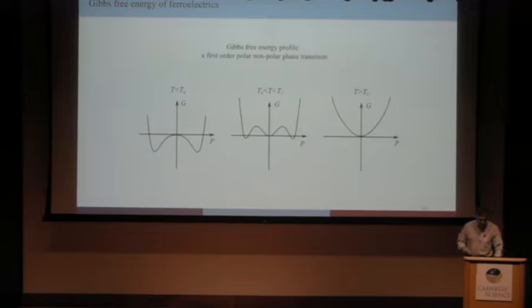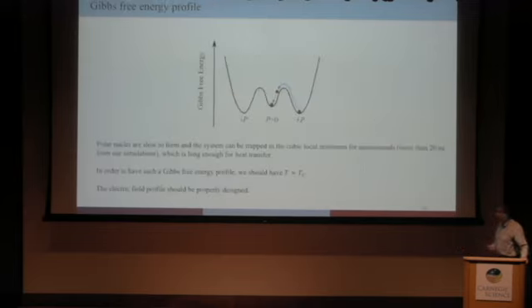And that opens this opportunity for using the latent heat. And so schematically, what we're doing with this electric field is we're driving the polarization away from its favored value, and for certain pulse shapes and durations, it can become convinced that the closest minimum is the p equals 0 one. It'll fall into that minimum and stay there for some amount of time. And depending on how close we are to the temperature at which the zero polarization minimum goes away, or becomes dominant over the positive polarization, that sets the time scale over which this can be metastable.